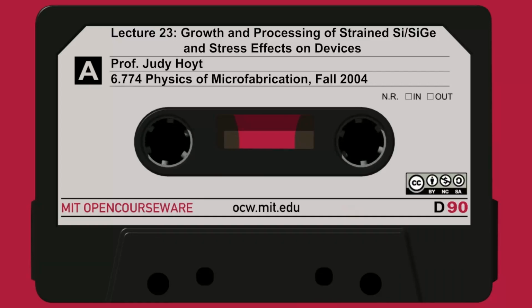Well, it turns out there's a technique called Raman scattering, which is an optical interaction. There are certain vibrational modes in the lattice that will scatter photons. And the Raman effect can be used to measure the strain, or the change in the lattice parameter, even in a very, very thin layer. So here's an example of a Raman spectrum from a MOSFET that was made. You're measuring the intensity of the scattered light as a function of the frequency in inverse centimeters. You see a large peak here associated with relaxed silicon germanium, and there's a small peak here, which is the thin strained silicon layer.